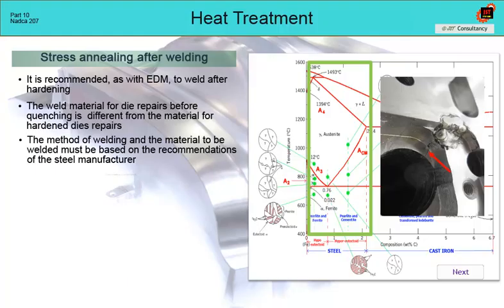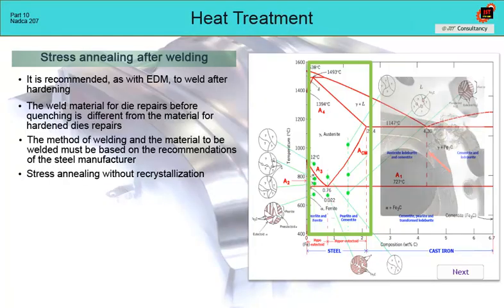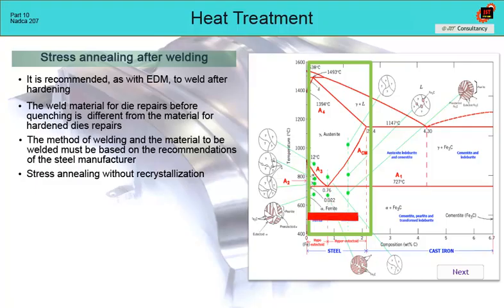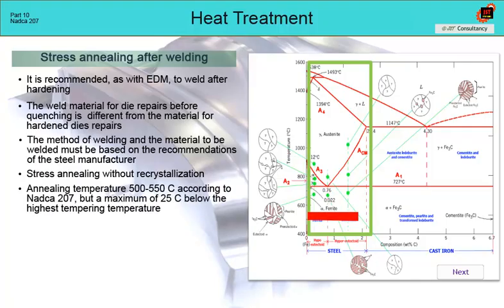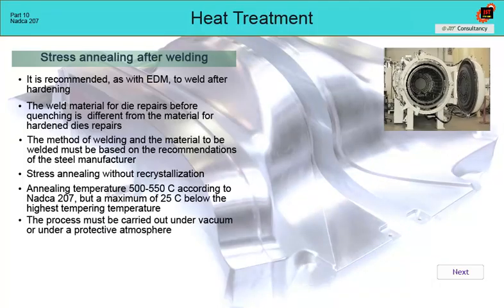The stress annealing is without recrystallization, at a temperature of 500 to 550 Celsius. The highest permissible temperature is then 25 Celsius below the highest temperature of the previous tempering. If it is welded after quenching, annealing must be strictly carried out in a vacuum or under a protective atmosphere, because it interferes with the already finished insert.